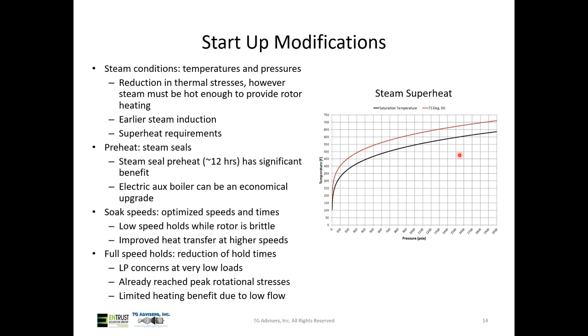So sometimes we put in a low speed hold, assuming it's allowable, such that we can get some of that heat soaking and we can let that steam to metal mismatch dissipate and that thermal stress come down before we increase to a higher rotational speed, which increases rotational stresses. And then, with high speed holds, the higher the speed, the better heat transfer, the quicker heating we get as well. And then eventually we get up to full speed. So we're at peak rotational stresses and we put load on the unit.